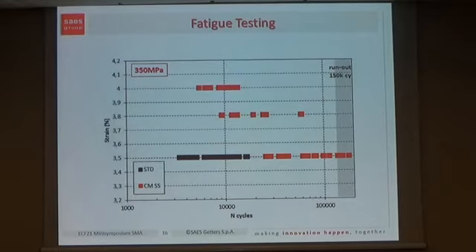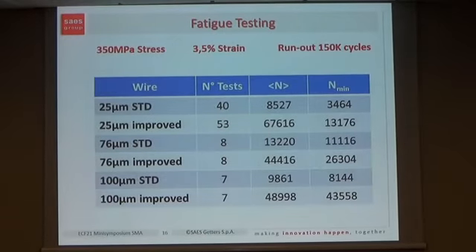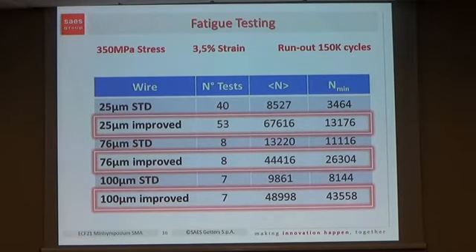In black, 3.5% strain is the maximum we are able to reach. The wires did not survive more than 1,000 cycles when increasing the strain amplitude of load. We fixed our run-out criteria at 150 K cycles, and these are the numbers. Just to give you again the numbers for these conditions: 3.5% strain, 350 megapascal stress, and you see that on 25, 76, and 100, even if in the case of 76 and 100 micron we still have to work to increase the statistics, the differences are quite evident, both on the average and on the minimum number. We are in the range of 2 times to 8 times the